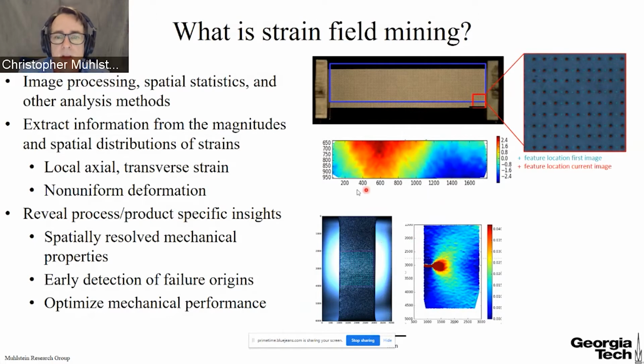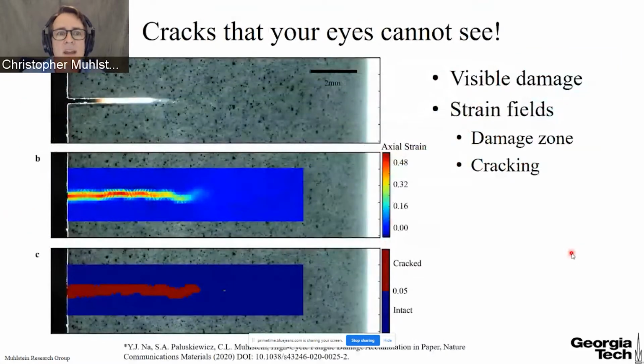And shown here in this lower image is actually a large strip of paper that has a notch cut in the side. And we can see on the right-hand side a picture of what the strain field looks like ahead of the crack tip. And this kind of information allows us to say important things about where defects are and how they grow, because then we can see cracks that your eyes cannot see.